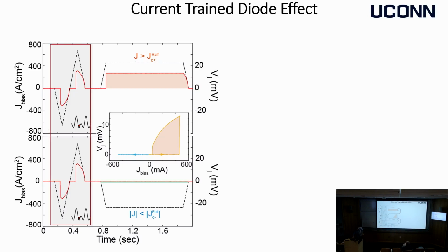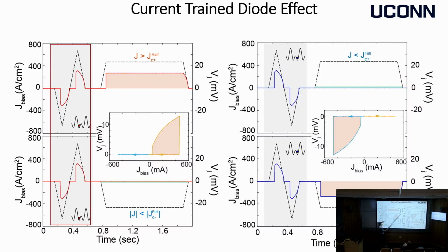To show the training, we do the following. We do the same kind of protocol, but we reverse what's happening in the preparation step. So basically, we just drive the current in the backward direction. Because it's just the same protocol but time reversed, we expect the direction of the diode to be exactly the opposite, and that's exactly what happens. So if we still apply the current in the same direction as the previous time, we see no voltage, but we see voltage in the opposite direction. So what has been observed experimentally is indeed that A, we have second harmonic, which is consistent with a phenomenological theory prediction, and B, that there's a trainable state which prefers one direction of the current versus the other, consistent with broken time reversal symmetry.